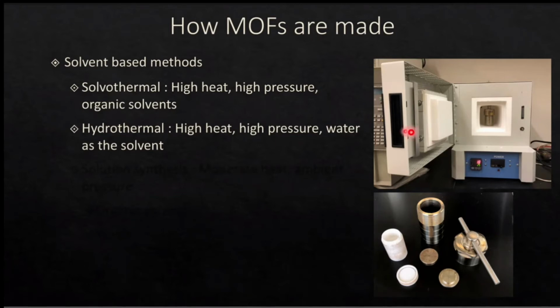So in this circumstance, we're going to use a furnace that looks something like this, and a pressure chamber that's going to stop our sample from exploding. So we have this Teflon sleeve here, and we're going to put our solvents and our reactants inside, and then we put that inside of the sleeve, and we tighten that down and put it into the furnace, where it's going to be heated above the boiling point of the solvent in order to increase the pressure inside of that sample. And that's going to make the formation of things that we can't make at ambient pressures and temperatures spontaneous.